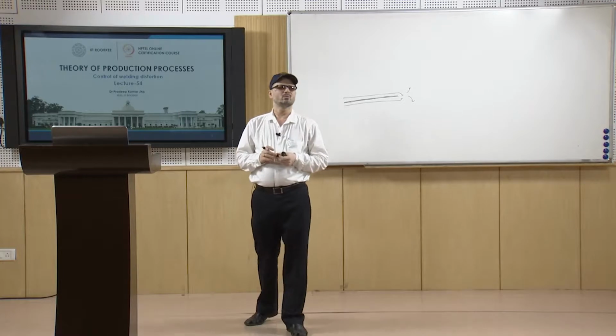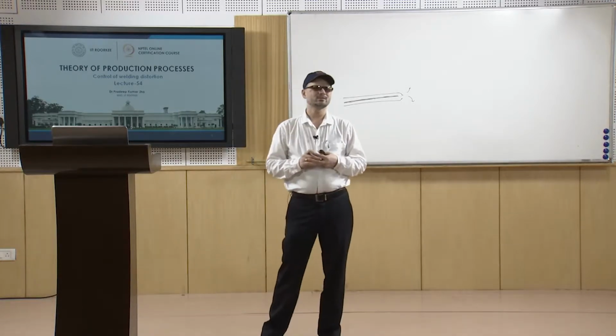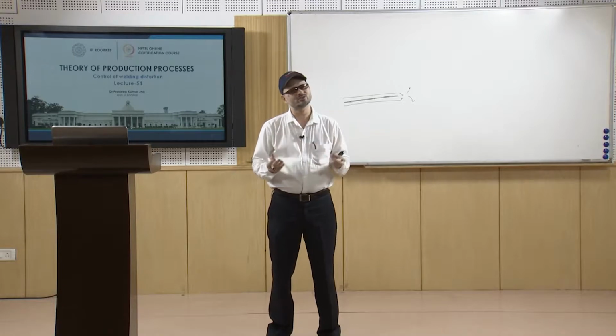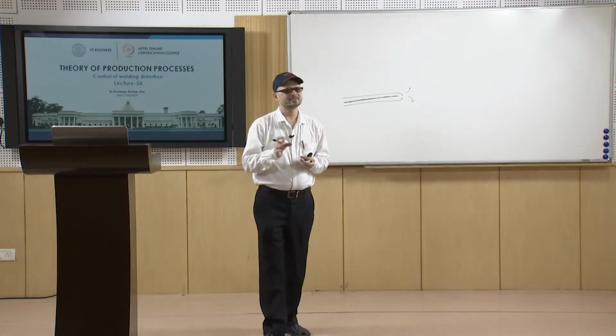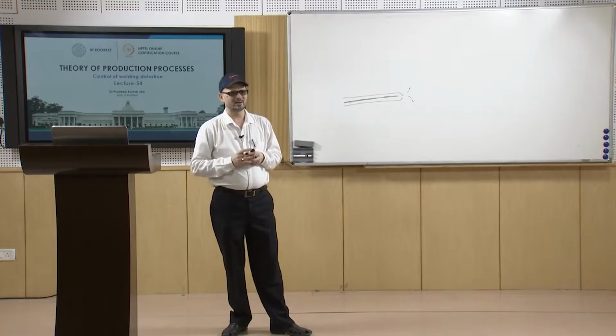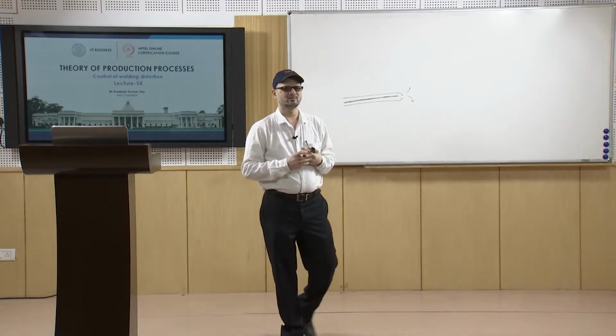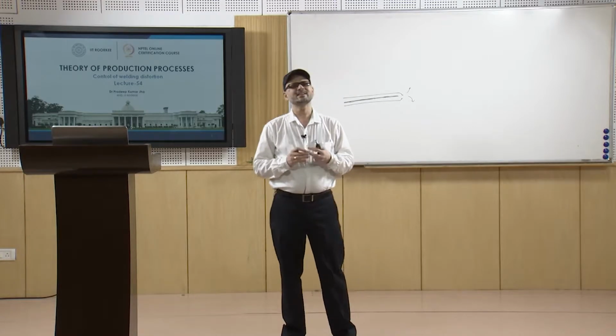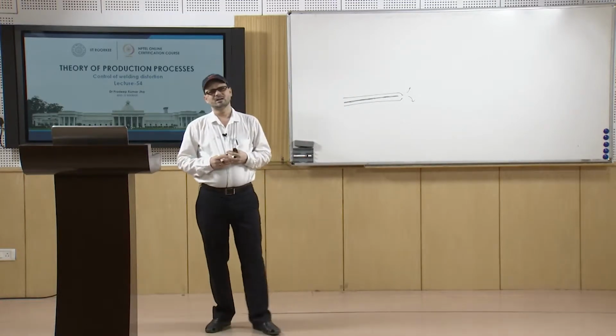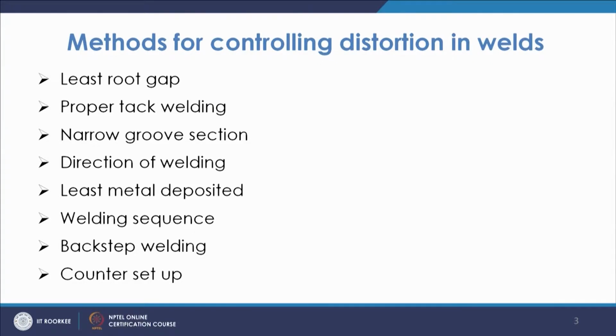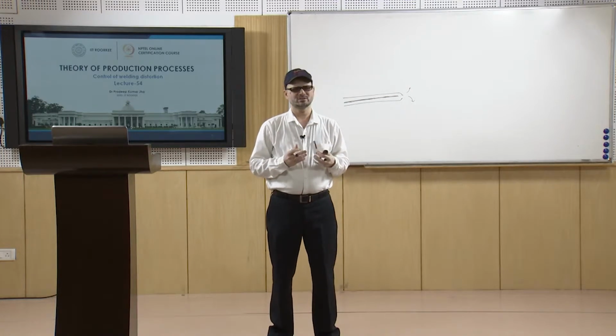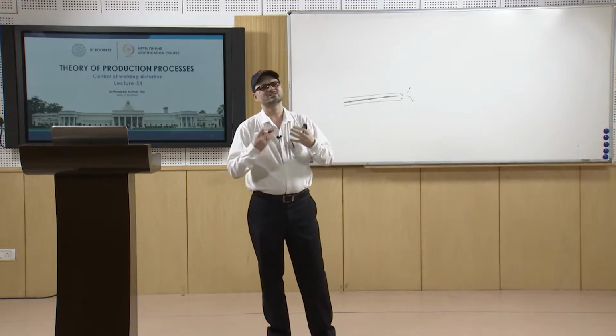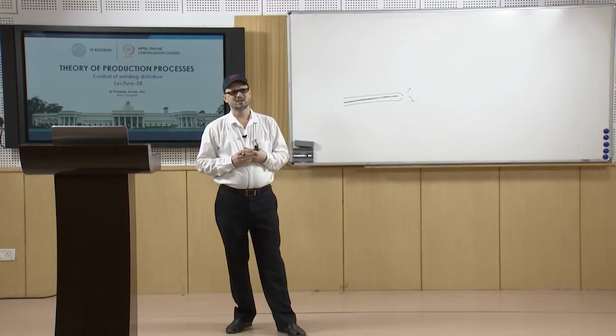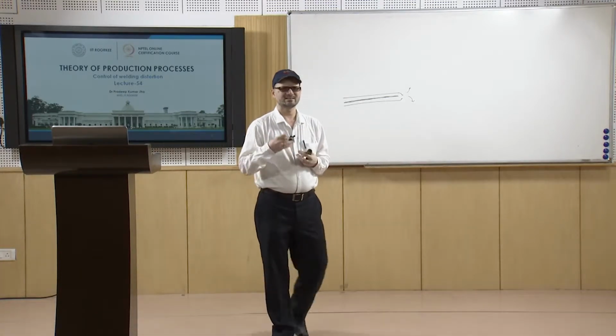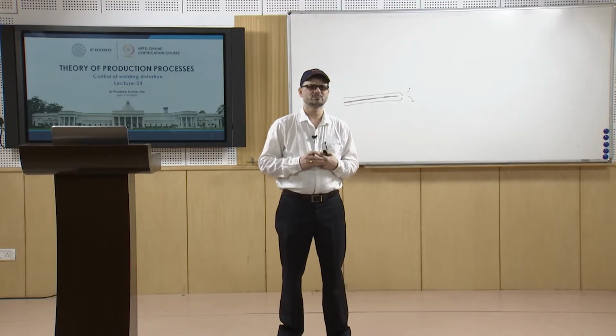Similarly, direction of welding, in what direction you are welding, what is the restraint, where is the restraint, so in what way you are welding, that is also important, in what direction you should weld, so that you have the minimum distortion generated. Then least metal deposited, again this is supporting the same principle, that if you have least metal which will be supporting the joint, then you will have least distortion. Larger will be the metal, larger will be the likely distortion. So, least metal deposition is another parameter which is important.